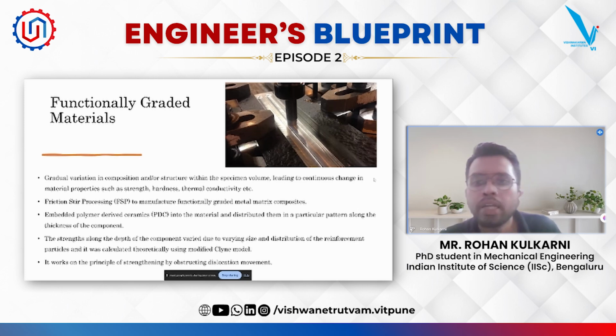We performed one experiment in IISc where we used a technique called friction stir processing to manufacture these functionally graded metal matrix composites. So what we did is we have something called polymer derived ceramics. So these are basically polymer particles, but when you heat these polymer particles at high temperatures around 800 degrees Celsius, then the organic part of the polymer evaporates, and what remains is the ceramic. So this ceramic acts as the strengthening component in your metals. So that's why we call it metal matrix composites.